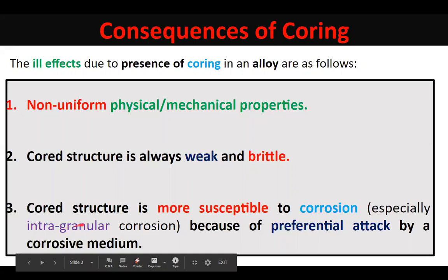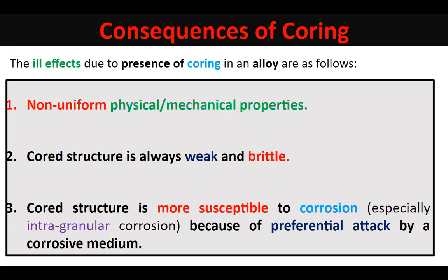Also, it has been found that because a true alloy didn't get formed at the grain boundaries, you don't have a proper homogeneous solution of the two constituent elements. Rather, at the grain boundaries, the areas near the outer fringes of the grains, you have more of the lower melting point constituent element.